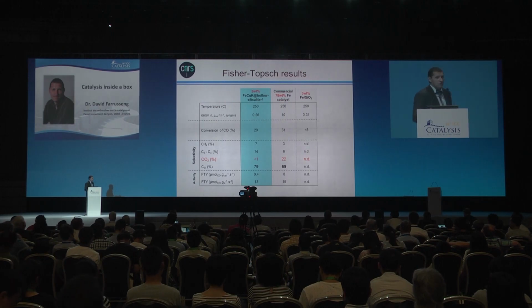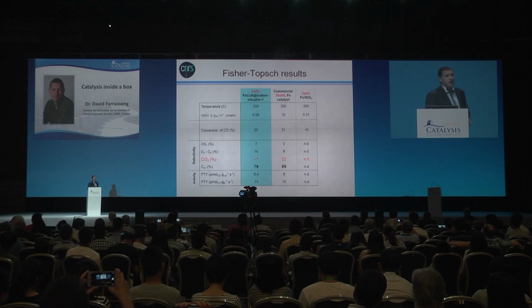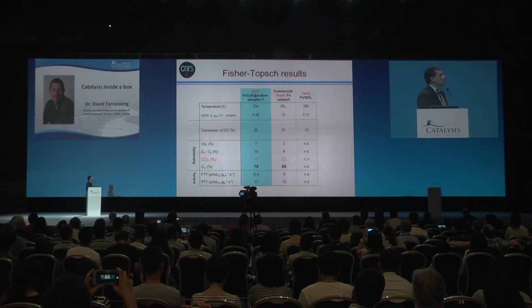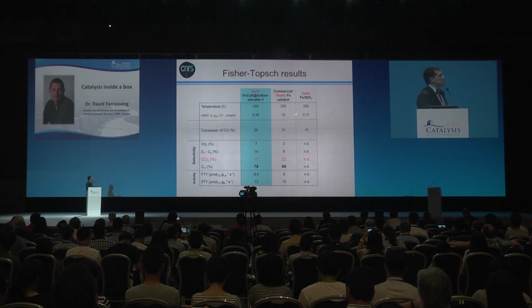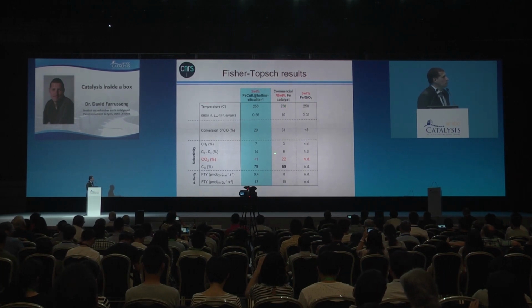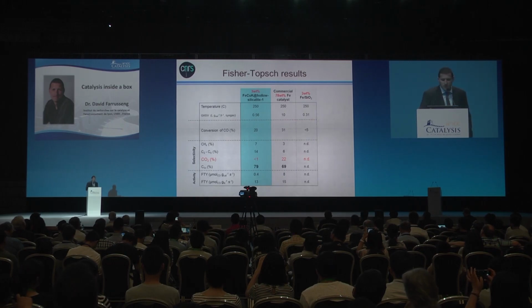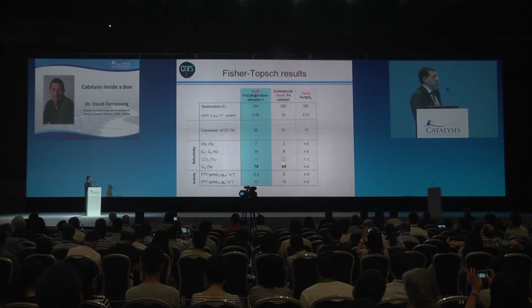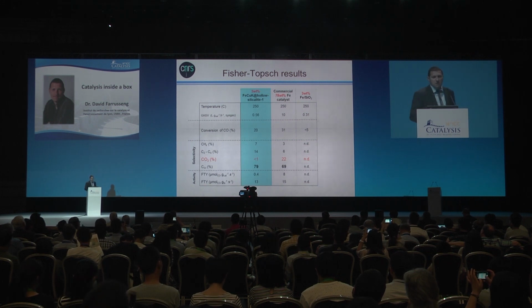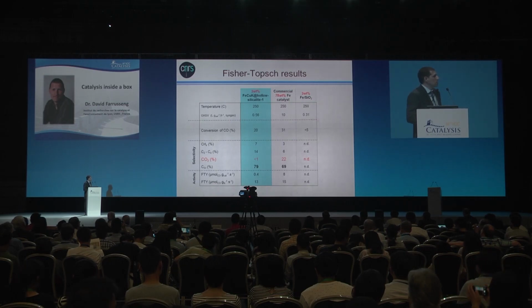Here are the results. You can see first a commercial catalyst, about 78% iron, tested at 250 degrees C, 30% conversion, light production of light hydrocarbons, and you see, as expected, 22% of CO2 and a very high selectivity in the liquid hydrocarbon fractions.